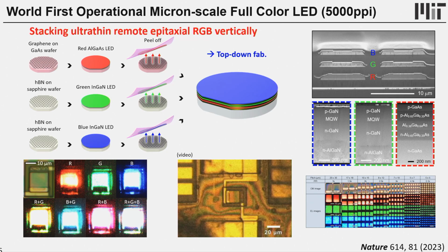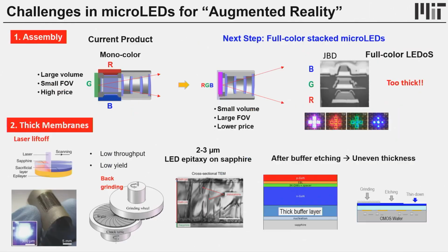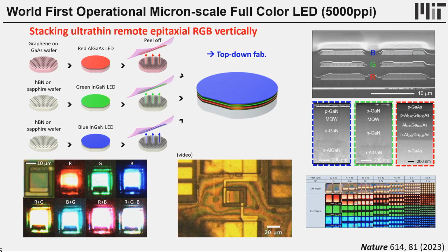Then we do monolithic 3D integration of RGB. Then there's no alignment issue, and our RGB is ultra thin. As you can see, compared to the one that you saw from JBD, our aspect ratio is low, and they're all perfect single crystal. Then we stack the highest pixel density micro LEDs here, 5,000 ppi. The colors are all well mixed. Thanks to the technique called remote epitaxy, we can peel them off in a very, very thin form. We can stack them up. Not only that,